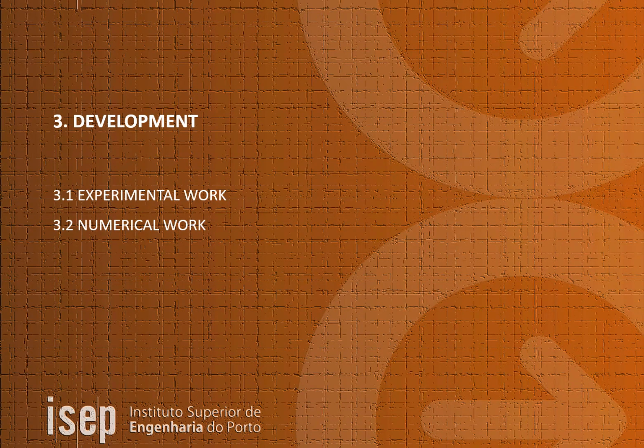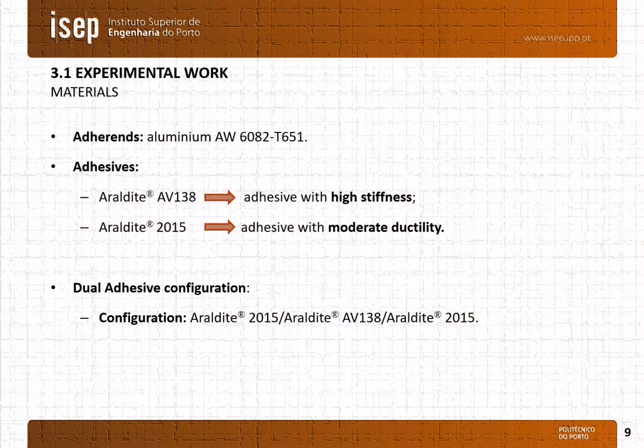Topic 3. Development, which is divided in experimental and numerical work. For the adherends was chosen the aluminum alloy AW6082 with a heat treatment. And the adhesives selected are the Araldite AV138, which is an adhesive with high stiffness, and the Araldite 2015, which is an adhesive with moderate ductility. The dual adhesive configuration is to use Araldite 2015 at the joint's ends and at the center the Araldite AV138.